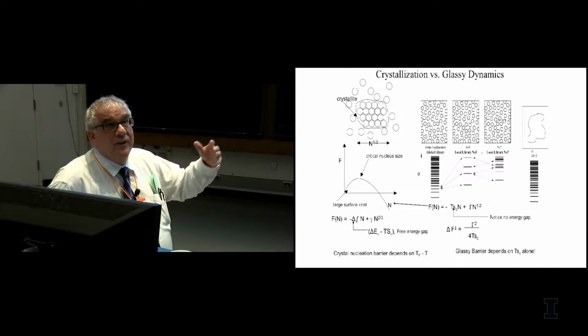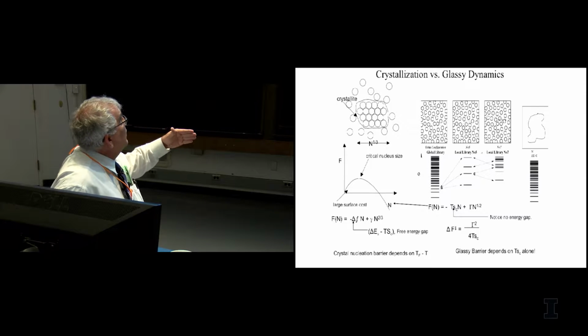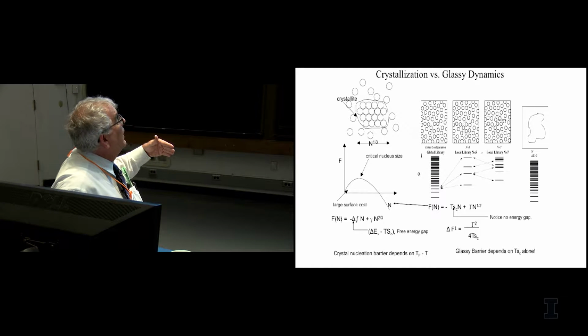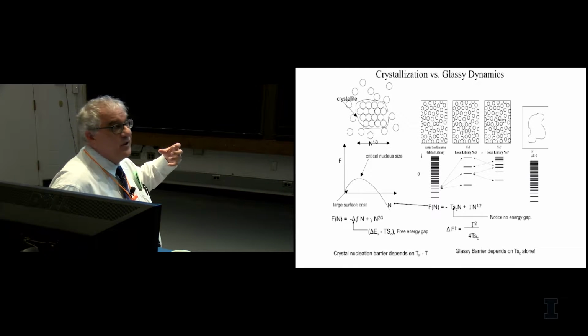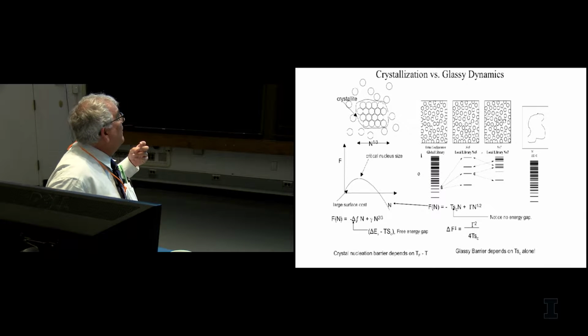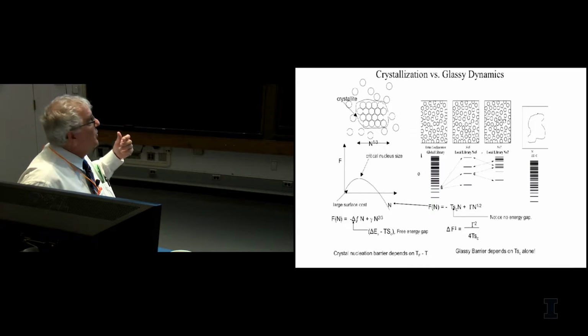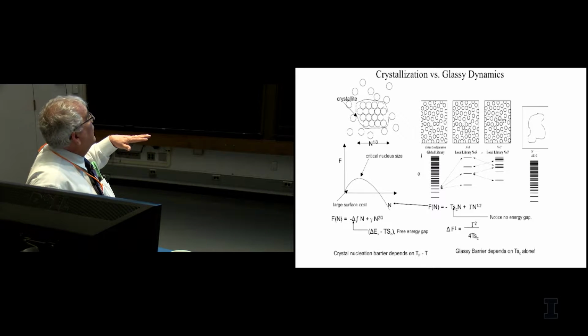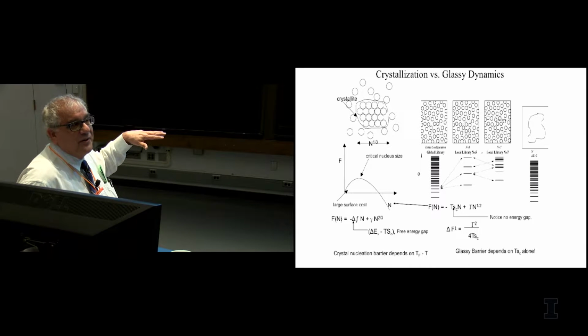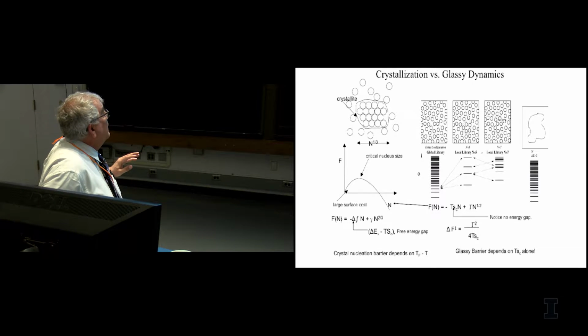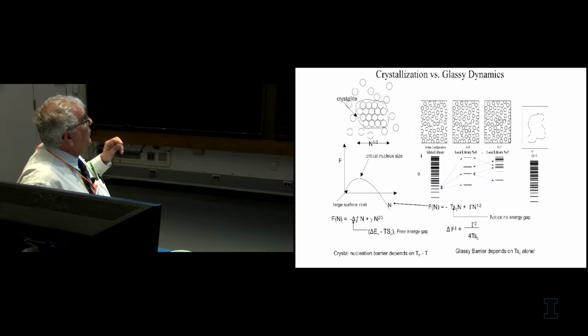And what happens is if you're in a high energy crystal, it will eventually form the lower energy crystal by a nucleation process. And there's a free energy, which is a function of how big a region gets turned over. It might favor the lowest energy structure by a certain amount, but it's costly to do this because there's this surface term. If you're nucleating a crystal out of a liquid, then the liquid is actually a set of different structures, and it's favored by an amount which is the configurational entropy. So this is more or less the Zeldovich-Frenkel theory of nucleation, of forming a crystal out of a liquid.